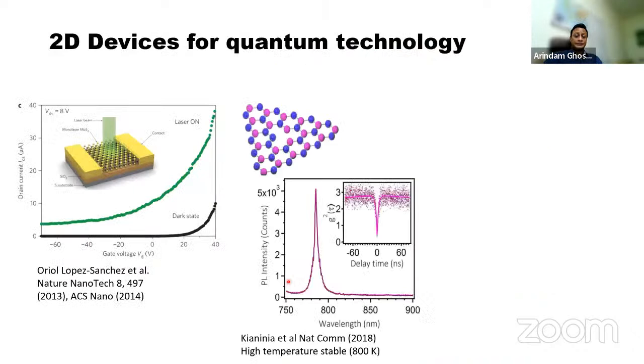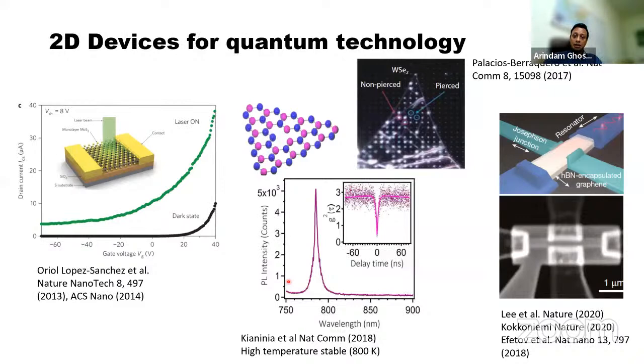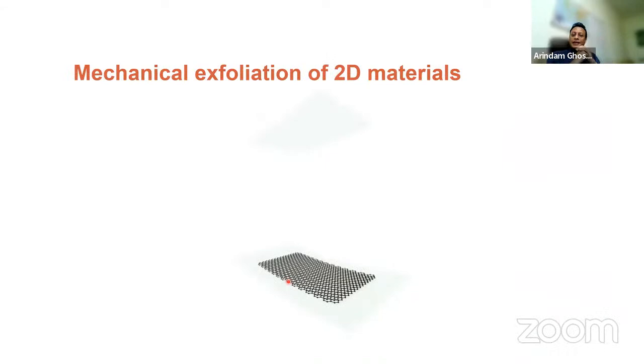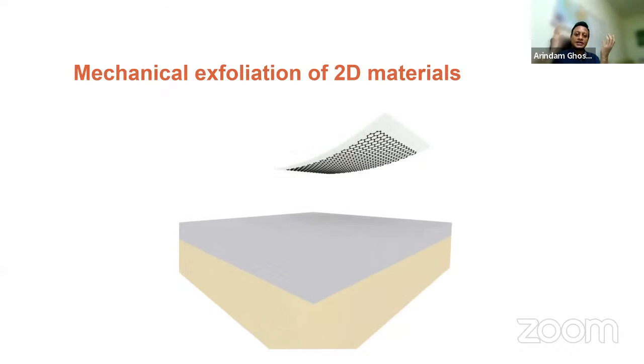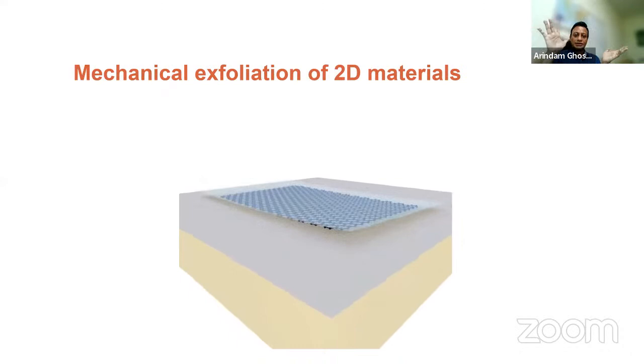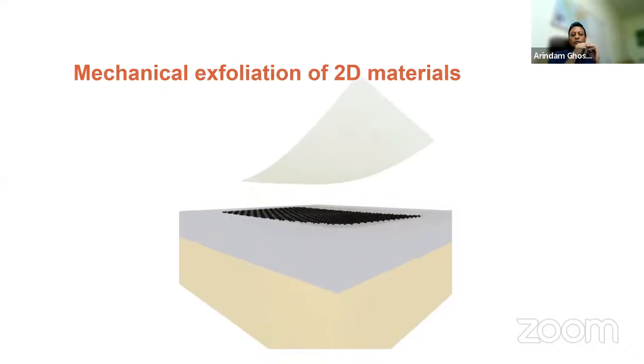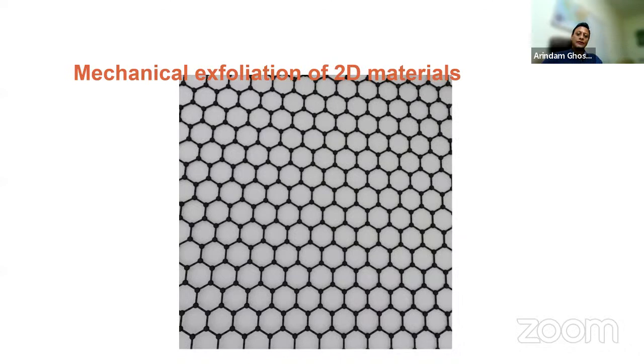They can be used, as I said, as emitters and bolometers in quantum technology directly in various devices. How do we mechanically exfoliate this? This is something which, in a simple video, essentially, mechanical exfoliation can be done in your laboratory. You take a chunk of graphite, for example. You use scotch tape, and then you essentially press that material on top of the substrate, which is a silicon oxide substrate. And then you leave a layer on top. This is not controlled, but there are now many, many different ways in which such two-dimensional materials can be created.